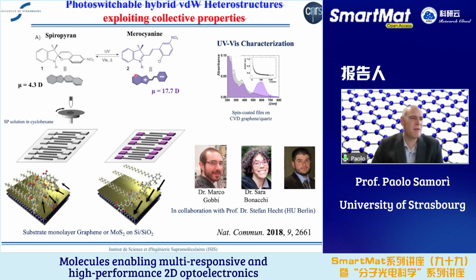Now, this work was done by Marco Gobbi, and the idea is that we took spiropyran with a long aliphatic chain. This R is nothing else than a C18, so an octadecyl chain. And we took spiropyran because it can undergo isomerization from the spiro to the mero form with UV light and can go back with visible light or thermally. And the two states have a very different dipole moment. So these are ideal to actually use this dipole effect for doping and de-doping our 2D materials on the bottom.